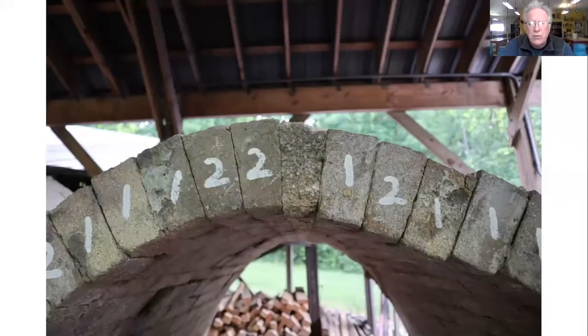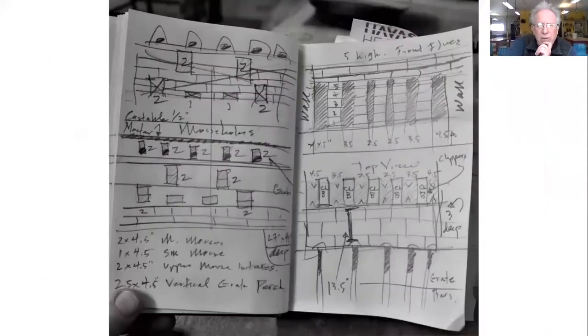the main firebox flues. Before we took the arches down, we went through and stripped and ground the fronts of the arches so that we could understand what kind of arch brick, because the different arch bricks have numbers. One arch is a little bit wider than a two arch, and they get narrower as the number gets higher. And the kiln was so coated with glass after those 30 years that it was hard to really get an idea of what kind of brick was there. So we did some grinding and then we identified those bricks.